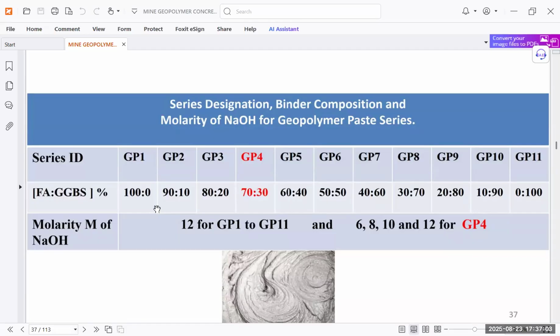So we make this as per the requirement, as we know different requirements are there. Similarly, different cements were there, like sulfate resistant cement and low heat hydration cement. In the same way, we can change the percentage of fly ash and GGBS, and the molarity also, to get the required effect of the geopolymer concrete. That is why we have done GP1, GP2 up to GP11, so that we change the fly ash to GGBS ratio and get the different required properties of the geopolymer concrete. And the molarity also we can change.